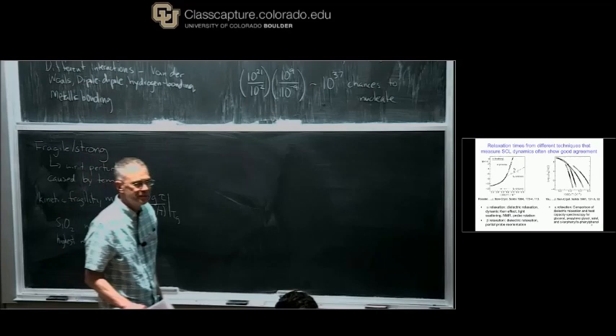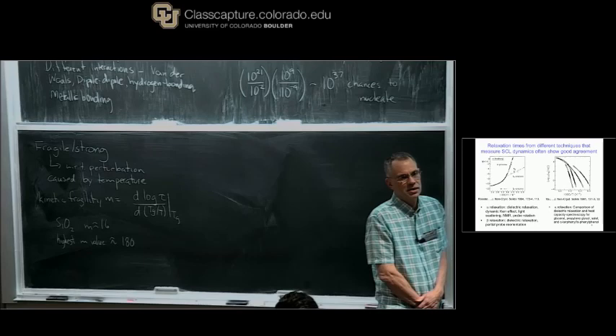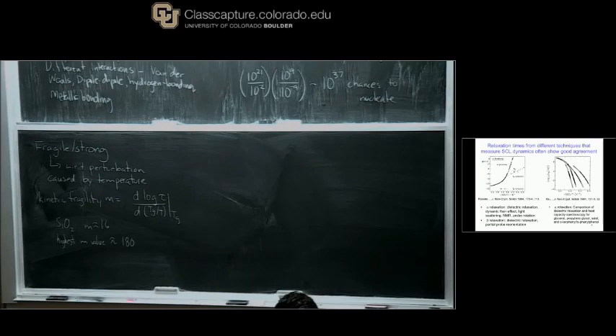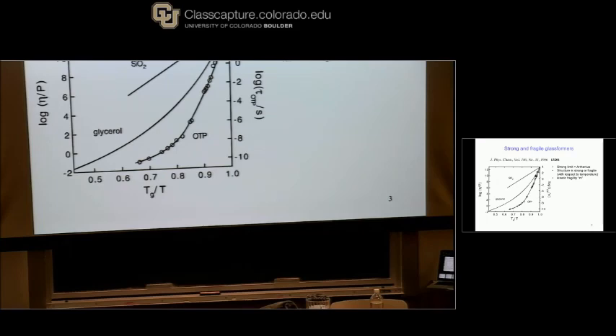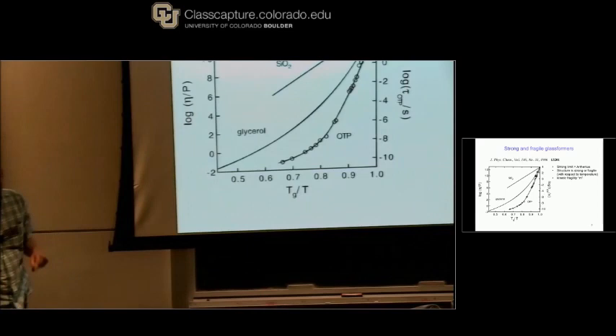On the previous slide, everything was shown in the supercooled liquid — fused silica is a glass. SiO2 can be a crystal; in the Angell plot, those are all supercooled liquids. People would also put the viscosity in to define fragility that way. Which of all these different methods and times are you going to pick to characterize your system? The good news is that to a first approximation, relaxation times measured from different techniques on the same material usually show good agreement. So it's not going to be such an important point whether we pick the viscosity or some relaxation time measured by a dielectric experiment.